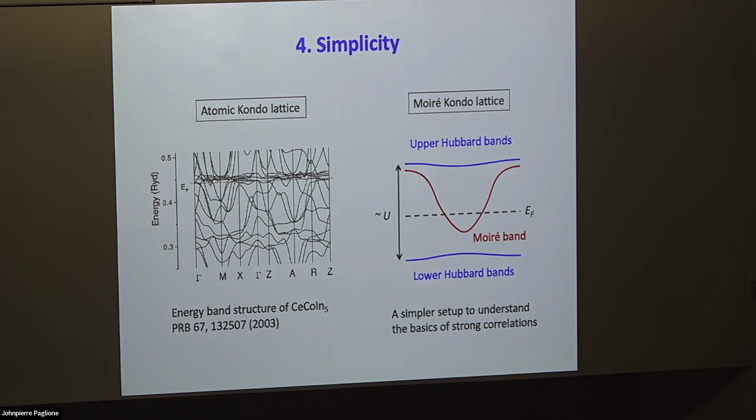Yes. So, what kind of excitons do you have in such systems? Excitons. Yeah, that's also an interesting question. It depends on whether the exciton binding energy is smaller or larger compared to the Moiré trapping depth. If the exciton binding energy is very large compared to the Moiré trapping depth, then the Moiré trapping is like a perturbation on the exciton. Then when you measure the optical transitions, they don't look particularly different from the constituent monolayer.